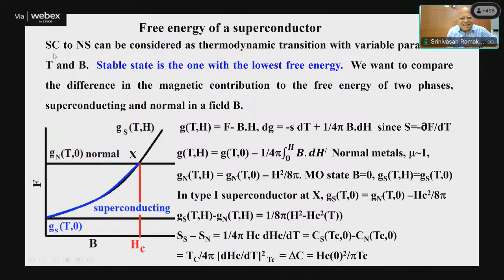Superconductivity and the normal state can be considered as a thermodynamic transition with variable parameters T and B. The stable state is the one which has the lowest free energy. So we want to compare the difference between the magnetic contribution to the free energy of the two phases, superconducting and normal. You can see that the Gibbs free energy in terms of the Helmholtz free energy is given by this expression, and you can get the Gibbs free energy for the normal state and the Gibbs energy of the superconducting state. You can see that below the critical field the Gibbs free energy goes down, and so the superconducting state is the stable phase. But as you increase the field, the Gibbs free energy of the superconducting state increases and becomes equal at the critical field. So it goes from a superconducting state to a normal state.